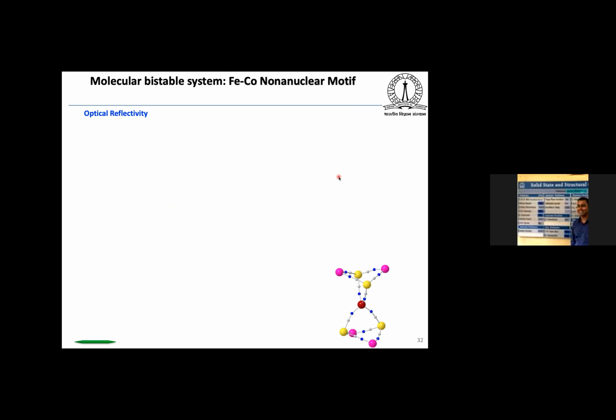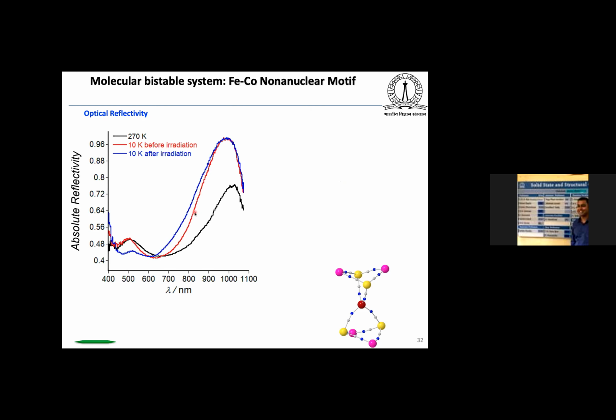And then we have performed the optical reflectivity measurements of the nonanuclear systems, where you can see the blue and the red curve, and there is a small light effect in these systems as well. You can see at 10 Kelvin we have observed some metal to metal electron transfer, but the effect is very weak in the case of this iron 4, cobalt 5 nonanuclear system.